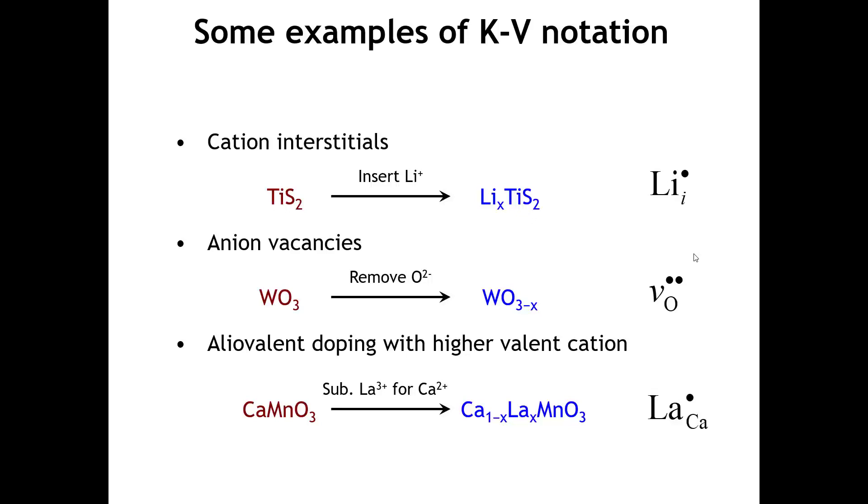In the last case, it's lanthanum going onto a calcium site, and because lanthanum has a higher positive charge by 1, plus 3 versus plus 2, this is a defect with a plus 1 charge.